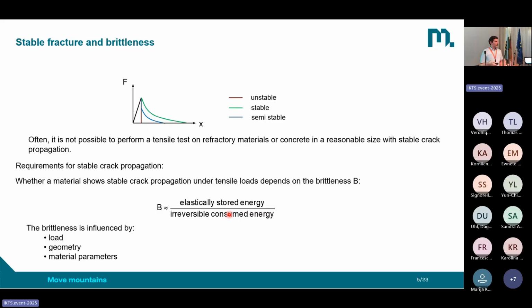And what is now influencing the stability of a fracture process in our sample? Basically, there is one important number. It's called the brittleness number. And how is it calculated? It's a relation between the elastically stored energy in the sample and the testing machine, divided by the irreversible consumed energy. This is the work of fracture, which is necessary to fracture your sample. So it could be a tensile test or a wedge splitting test as well. And how is this brittleness influenced? Influenced by load, geometry, and material parameters.